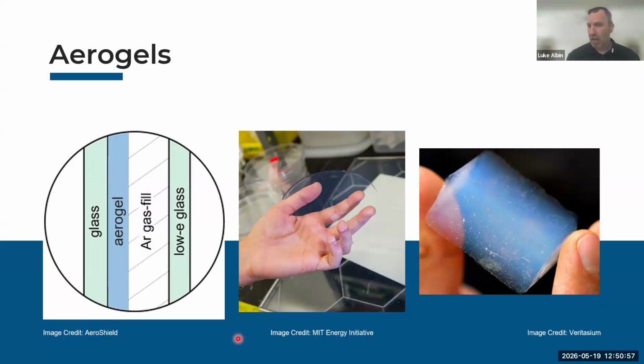The same idea still applies. We're trying to fit it into that dual pane system. So when you take a look at a cross section, you've got the glass, the aerogel, which again is the solid, you still have a gas fill area, and then another piece of low-E glass. So again, as heat tries to transfer through, this additional solid is a really super insulator. I had mentioned NASA; they use it on thermal blankets on spacecraft.